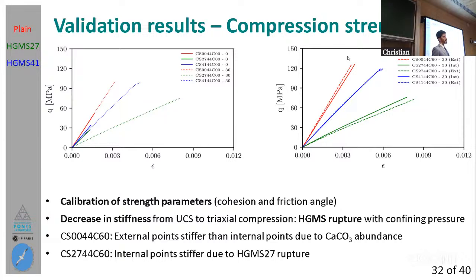So let's begin with the easiest, which is the red one. There you will see that the inner part presents a lower stiffness than the outer part. This is related to the precipitation of the calcium carbonate crystals in the outer part, due to the greater extent of the changes in this outer part. And since the calcium carbonate is more rigid, it will increase the stiffness of this part of the material.